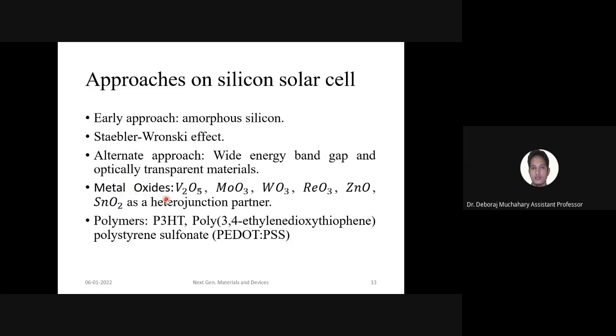Of course, these materials include vanadium pentoxide, molybdenum oxide, tungsten trioxide, ReO3, ZnO, and SnO2. These are some oxides: transition metal oxides, and zinc oxide and tin oxide. These materials have good wide band gaps as well as good transparency. In zinc oxide, you will find around 90% transparency, even more than that; it depends on the fabrication conditions, but the transparency is quite high. And the band gap of zinc oxide is around 3.3 electron volt. Likewise, the band gaps of these materials are wide and the transparencies are good. That is why they have been investigated as a partner to the silicon.